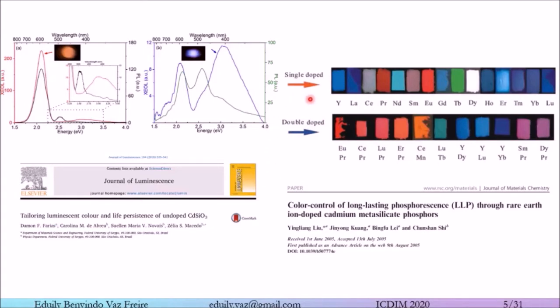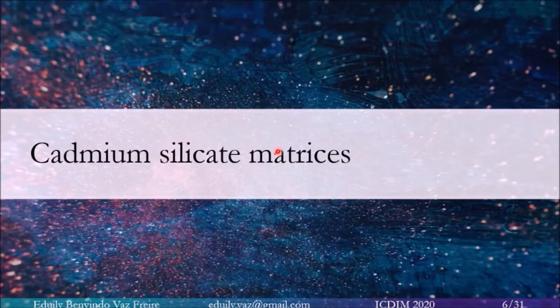Okay, in the CdSiO3 matrix, single doping can be made. That is, use only one dopant and obtain emission colors in different regions of the visible spectrum. But we also find many works that dope double and obtain luminescence in other regions of the visible spectrum. This fact is of great interest because it makes it possible to choose the doping ion according to the desired luminescence colors.